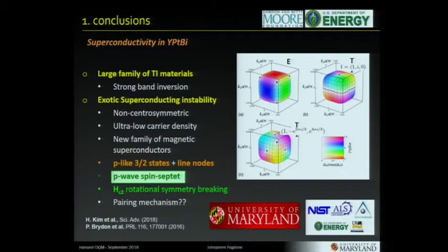I showed you just briefly for the palladium series. You can do that for platinum too. It's the same thing. So you can have coexistence of time reversal breaking magnetism, superconductivity, and the topological band structure. And then in this particular case, we studied extensively. We've shown evidence of these P-like J equals 3/2 states. Taking that band structure together with the existence of line nodes from experiment leads us to this prediction that it's actually a spin septet, or dominant septet state.